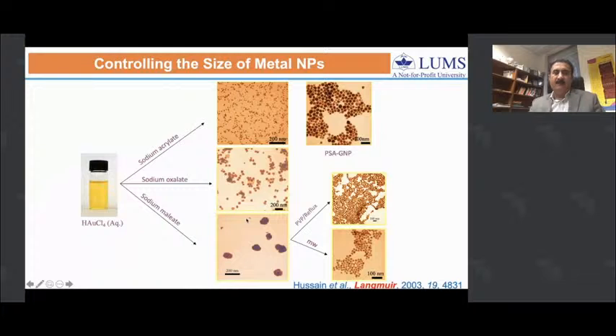Here, instead of sodium citrate, we explored that we can use a variety of other mild reducing agents and stabilizers like sodium acrylate, sodium oxalate, and malate, and then reduce gold salt into gold nanoparticles. In this way, we were able to prepare particles that range in size from 10 to about 100 or 200 nanometers.